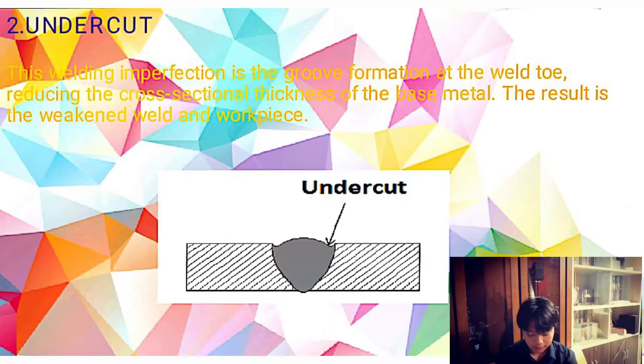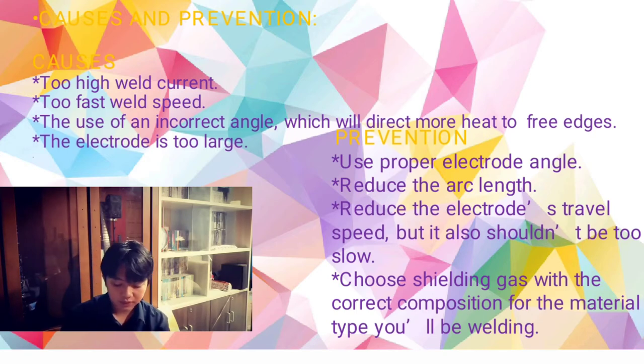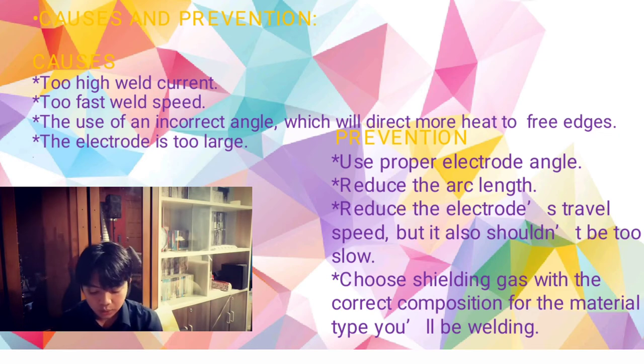The second is undercut. This welding imperfection is the groove formation at the weld toe, reducing the cross-section thickness of the base metal. The result is a weakened weld and workpiece. Causes and prevention. Causes: too high weld current, too fast weld speed, the use of an incorrect angle which will direct more heat to free edges, and the electrode is too large.